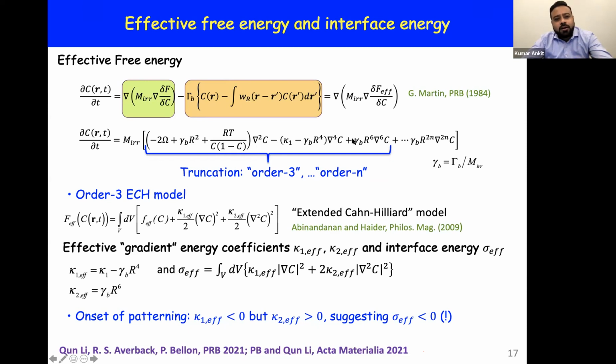How do you, by the way, calculate the mobility? Is the mobility the diffusional mobility, or is it something that is also impacted by the momentum imparted by the flux? That's a very good point. Usually we end up having to derive that mobility from other models in general, because mobility here is affected by the concentration of point defects, and under radiation you create point defects, so the mobility goes up. It's known as radiation enhanced diffusion. That's why it has a superscript irradiation here, to capture that it is modified by irradiation. And so it becomes challenging or complicated.